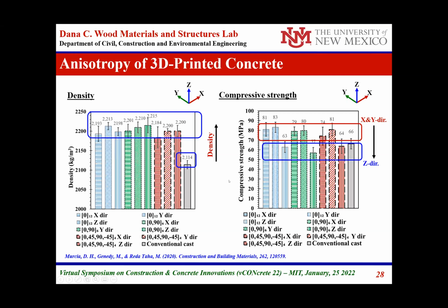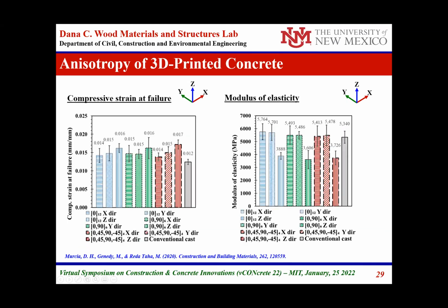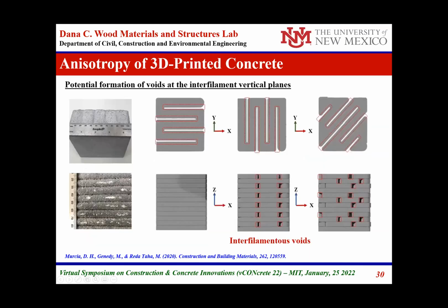All these observations, when done with multiple measurements, about 5 samples, include statistical variability testing to make sure that when we say something is lower, it is statistically lower. We did the same for strain at failure and also interestingly for the modulus of elasticity, which shows the exact same behavior.